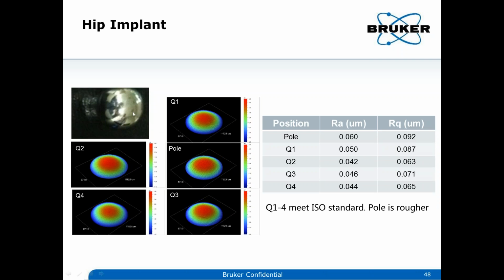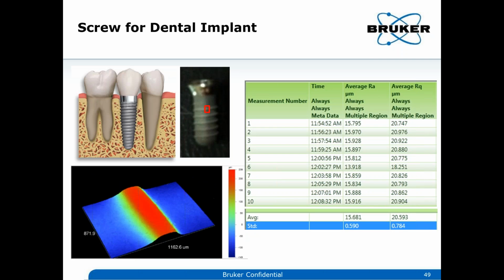Similarly, you can measure the pole roughness and then the roughness at different points, and you can control them, and you can see, well, the pole is slightly out of tolerance, right? Much rougher compared to the other points. So probably they need to optimize the processing to get the roughness of the pole down, right?